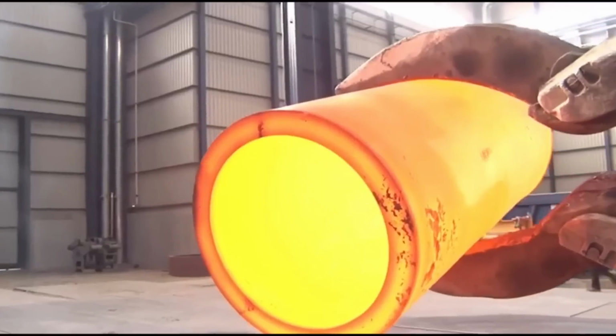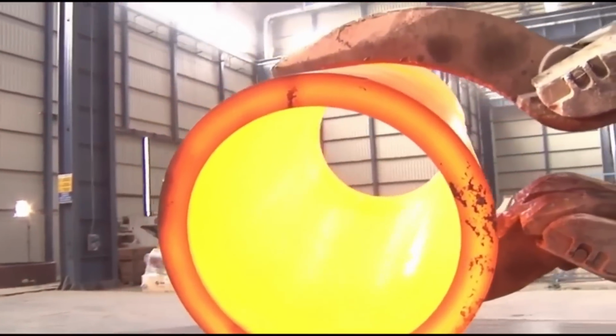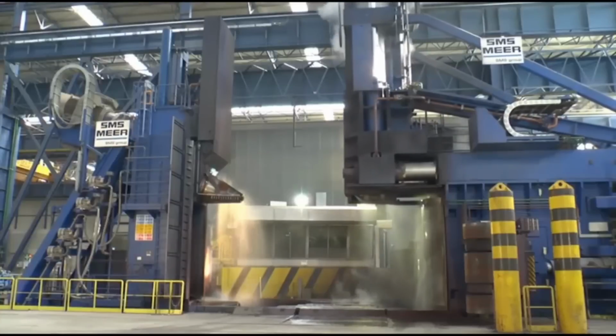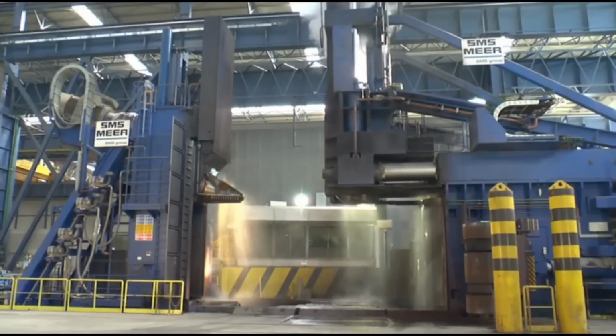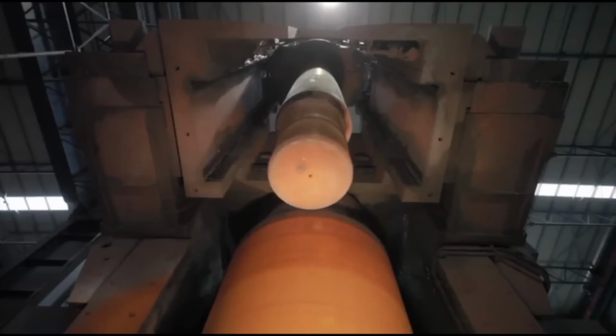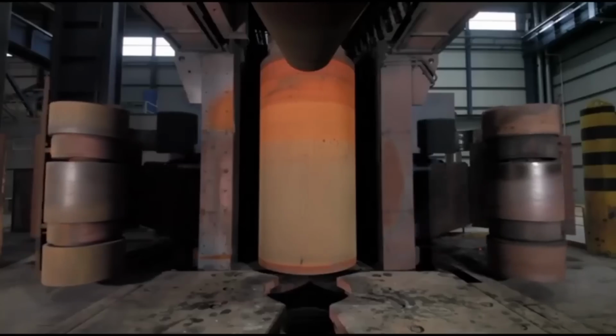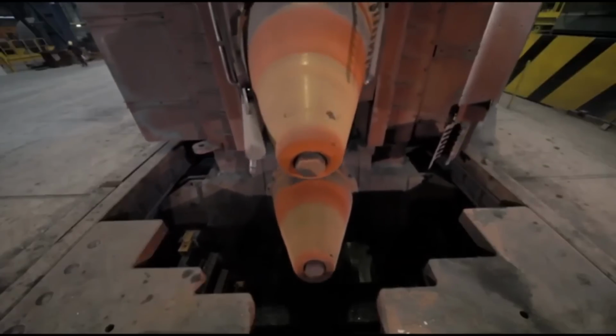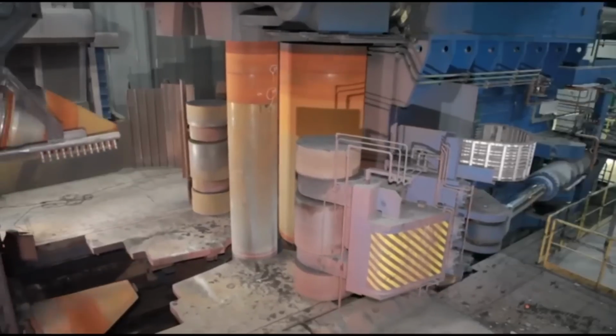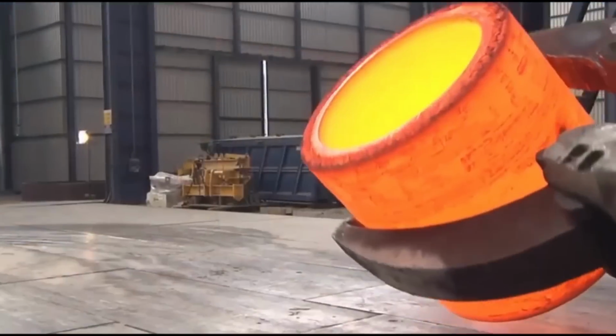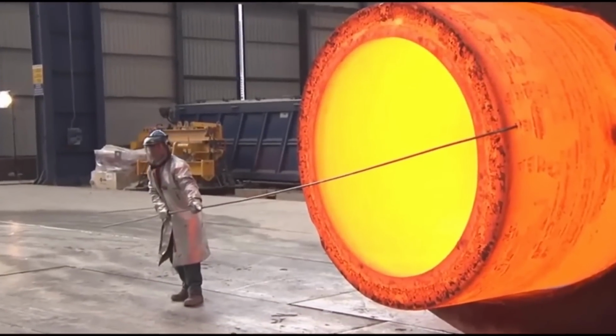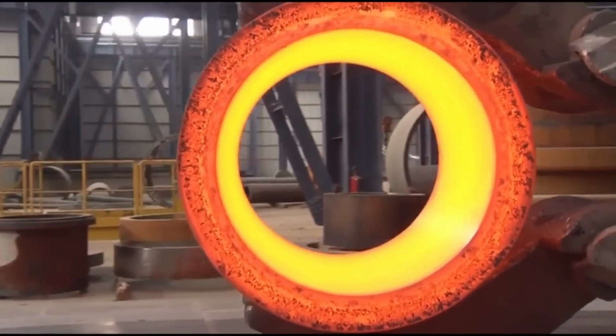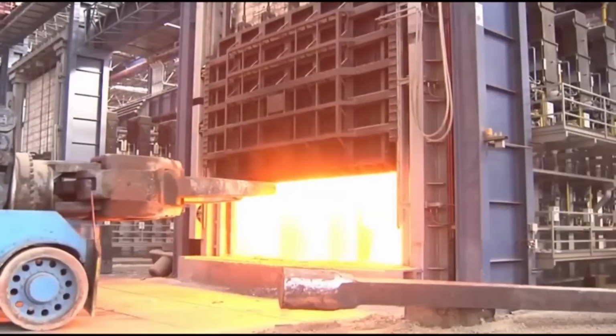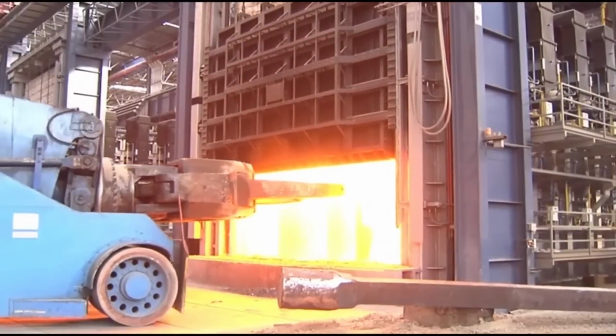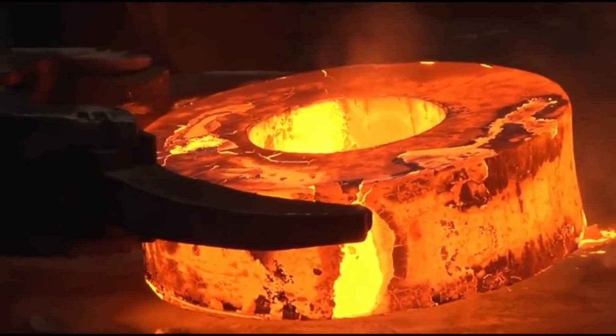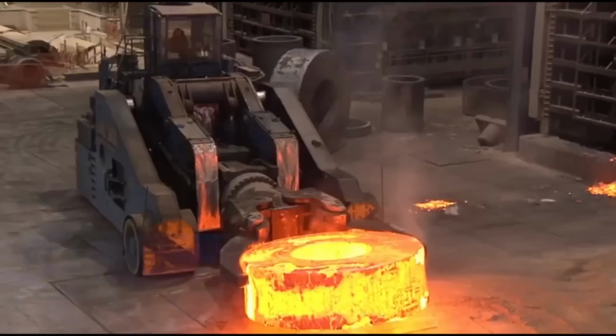The slight reduction in height from 3,999 millimeters to 3,986 millimeters indicates a controlled compression in the axial direction. The rolling time for this process is recorded at 214 seconds, and the final weight of the ring is 27.6 tons. The rolling process not only changes the dimensions, but also enhances the material properties, improving the ring's strength and structural integrity.